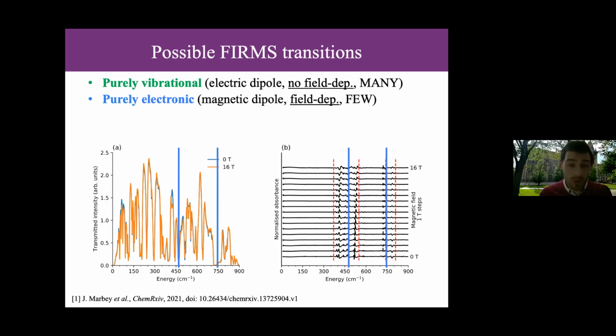Then we, of course, have the purely electronic transitions, that is going between the different Kramers doublets of the crystal field split states. And these would be magnetic dipole allowed transitions. Now, magnetic dipole allowed transitions are much weaker than electric dipole transitions, which is a well-established fact, which is why you need resonant cavities in EPR, and you can't just do free space EPR. I mean, you can do free space EPR, and people do at very high powers, high frequencies. But essentially, magnetic dipole transitions are far, far weaker than electric dipole ones.